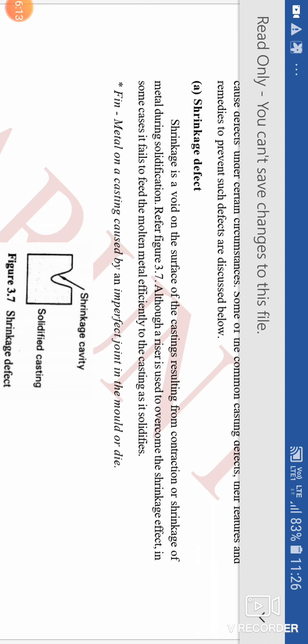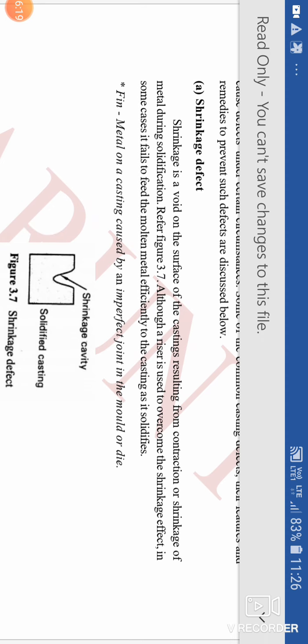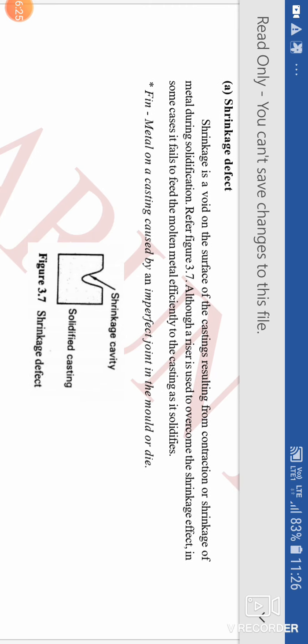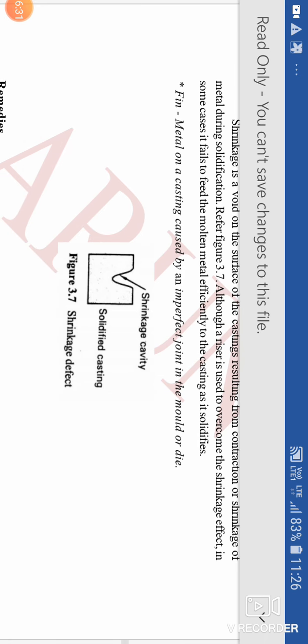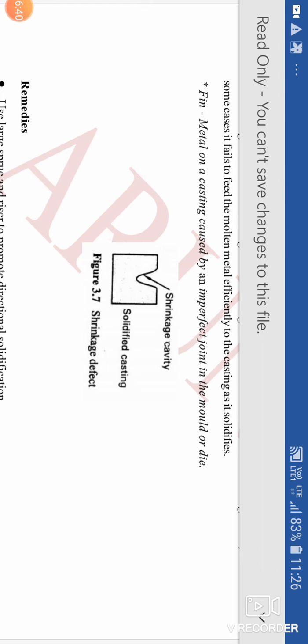So this is very important. Shrinkage is a void on the surface of the casting resulting from contraction or shrinkage of metal during solidification. Refer figure 3.7. Although a riser is used to overcome the shrinkage effect, in some cases it fails to feed the molten metal efficiently to the casting as it solidifies. So here a shrinkage cavity is formed in the solidifying casting. Fin is metal on a casting caused by an imperfect joint in the mold or die.